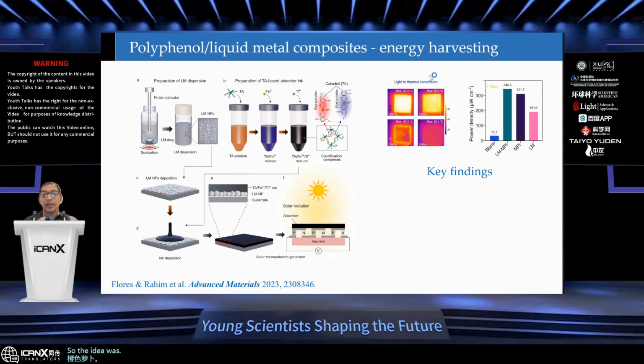So it is light absorbing in the visible range. The idea was, can we use this absorption and also use the liquid metal's metallic conductivity to create a system which can give you a solar thermoelectric generator under solar irradiation? And interestingly, in this paper, we showed that our system was so good. You can see on the right side that when it is under light, the temperature goes up really quickly, to almost 60 degrees in about 30-40 seconds. So that was really a good composite.